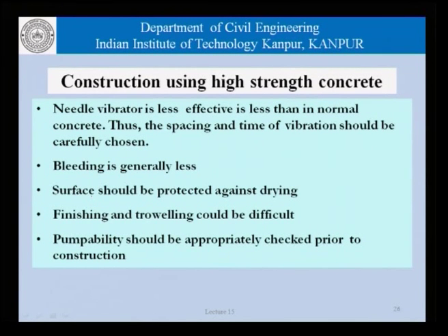The bleeding in high strength concrete is less. The surface should be protected against drying, because the surface which is susceptible or vulnerable to drying anyway, if that happens in high strength concrete, the reduction in strength could be very drastic, and that is why we must make sure that the surface is protected against drying. Finishing and troweling is difficult.